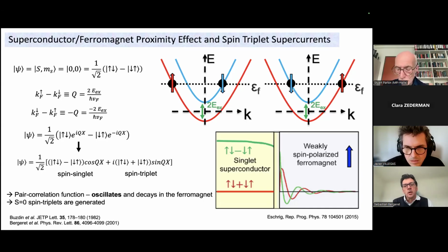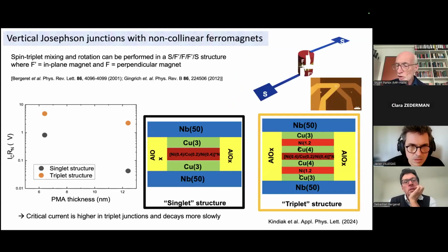And what Sebastian proposed was that if you have a second magnetic layer orthogonal to the first one, it would allow the traveling of triplet pairs, the triplet component of the superconductivity, over long distances. So you could use this non-collinear magnetization to generate triplet supercurrents. I just wanted to show you some of our own experiments in this regard, and this is by Ivan Kindiak, a PhD student of mine.